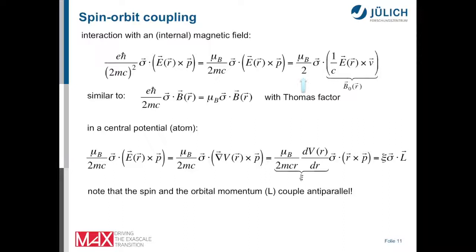And therefore, without spin-orbit coupling, if you calculate the solid, you don't get an orbital momentum, because the crystal field quenches all this to zero. So the spin and the orbital momentum, they couple anti-parallel, so it's a little bit different than a usual coupling between two orbital momenta.